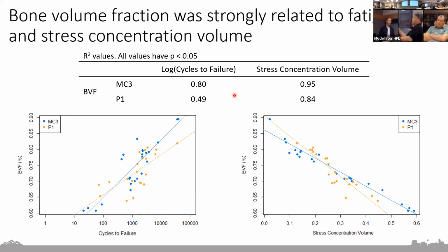So the next thing we looked at was bone volume fraction. And we found this to be pretty strongly related to the fatigue life and stress concentration volume of both of our bone samples, which we thought was a nice finding, was what we expected. But one thing is, although bone volume fraction correlated really nicely for both bones, the bone volume fraction actually looks quite different for each one.